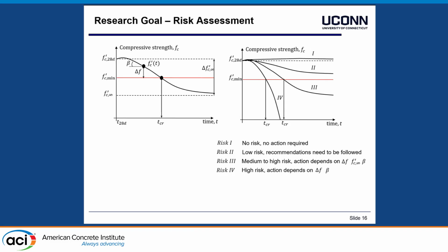You could think of 4 different scenarios. You don't have any pyrrhotite or don't have any deterioration over time. Then we are here, scenario 1, everything is okay. And the concrete increases its strength a little bit over time. If the deterioration comes from the pyrrhotite oxidation, but we don't have as many sources in there to lead to deterioration, we might have a decrease, but it levels out and we never reach the minimum. Then you could also say, well, it is still fine. We don't need to be concerned about the structural integrity of the foundation. But if we have too much of sources there, then we might go under the minimum strength at a certain time. The question would be, when would this be? Or we have so much that the curve will never level out, will never be stable, and it would just deteriorate. So those houses would then be at a high risk.